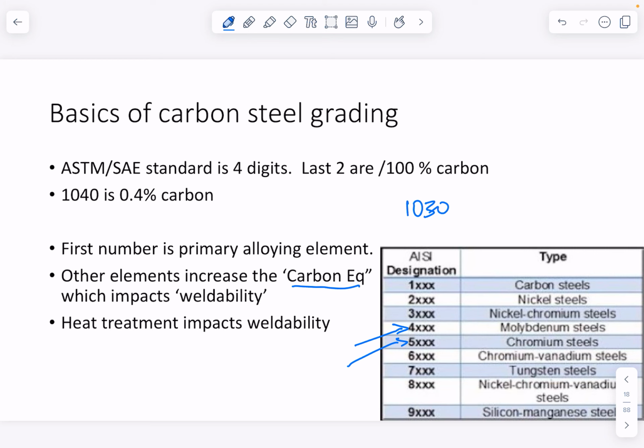But if I'm looking at this guy here, the 4140 or 4340, that 4 and the second number add effectively to the carbon equivalent. So anything up to 0.4% is deemed as readily weldable. Beyond that, you've got to do specialised processes of preheat and post-heat and other such things. So you just need to be mindful that there are these other things out there in the world.